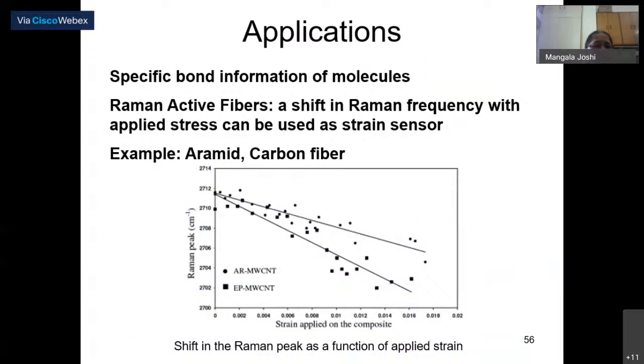So the applications of Raman spectroscopy are that specific bond information of molecules is possible. Then there are some Raman active fibers, and carbon nanomaterials are found to be Raman active. Suppose in this fiber you have used multi-wall CNT, and the multi-wall CNT samples on aramid or carbon fiber have been shown, and strain has been applied onto the composite, and the Raman peak changes with the change in strain. Suppose you are applying this CNT nanomaterial onto a fiber and then you are straining it. When you strain it, the interactions of the carbon nanotubes or whatever you have imparted will change, and so there will be a change in the Raman peak. And this can give you information about whatever you are looking at. Maybe it will lead to a change in the conductivity of the sample or anything else.